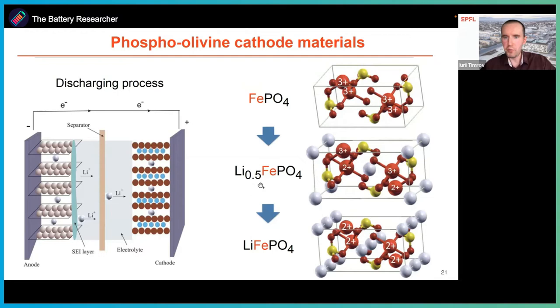And as you can see, I highlighted that the fully delithiated material has iron all in the 3+ oxidation state. And at the bottom, iron is in the 2+ oxidation state. However, the intermediate structure has a mixed valence phase where we have both iron 3+ and iron 2+. So let us look if we manage to describe this challenging case of mixed iron 2+ and 3+ with standard DFT and also using DFT plus Hubbard.